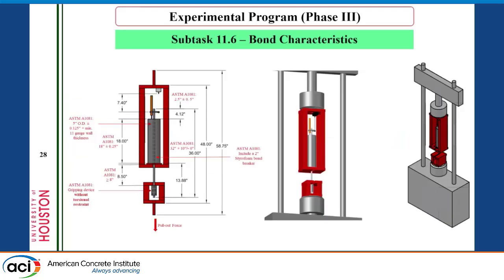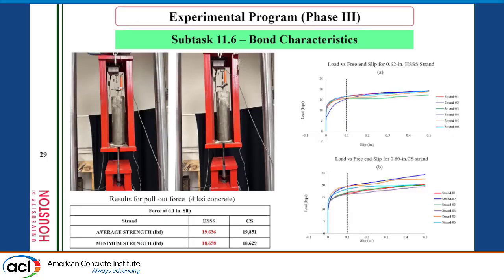The same thing for the bond. The ultimate goal of this project is to have design guidelines for bridge elements when we want to use this stainless steel strand. So we did the same thing. We followed ASTM. We used the mortar, and also for further investigation we used concrete, with different concrete strengths. And we found similar results.